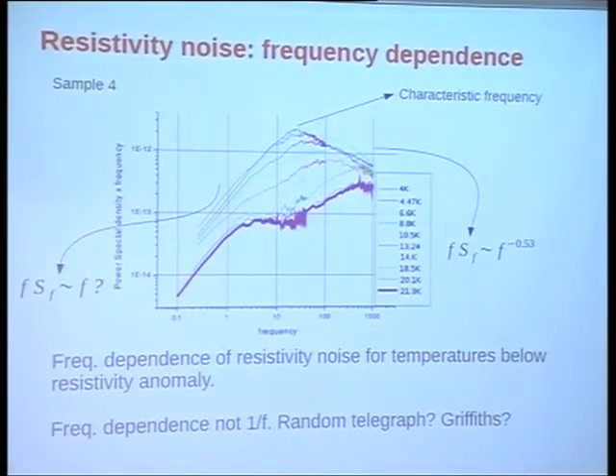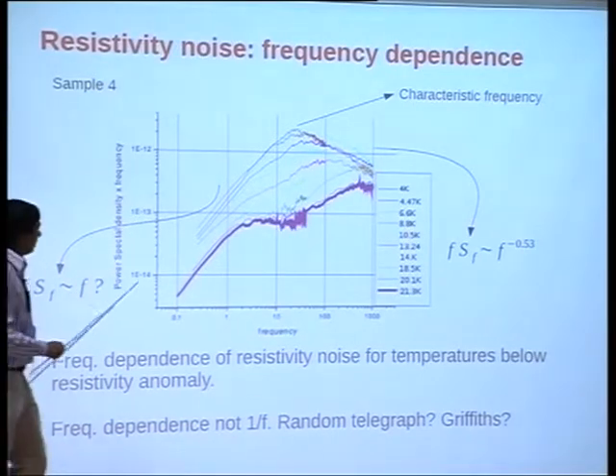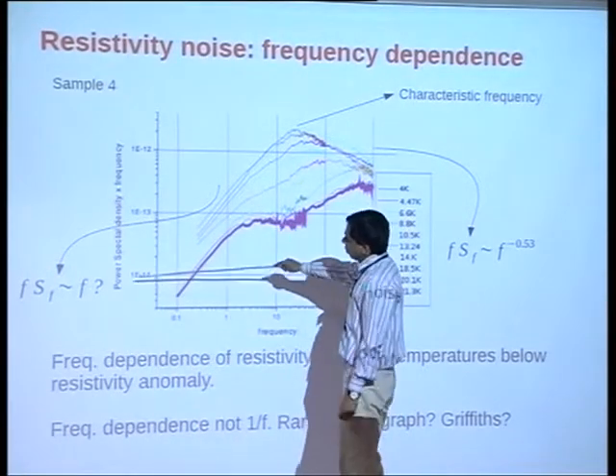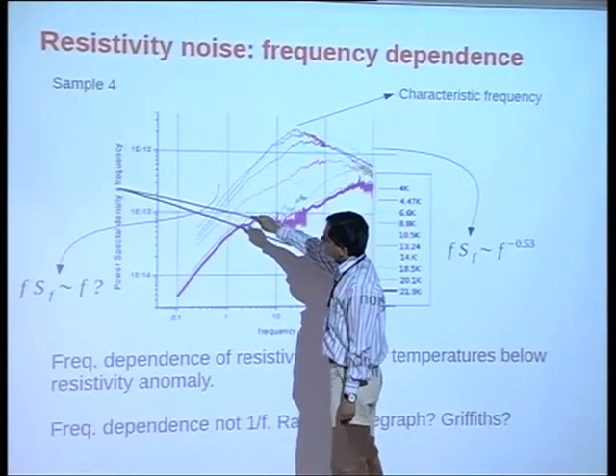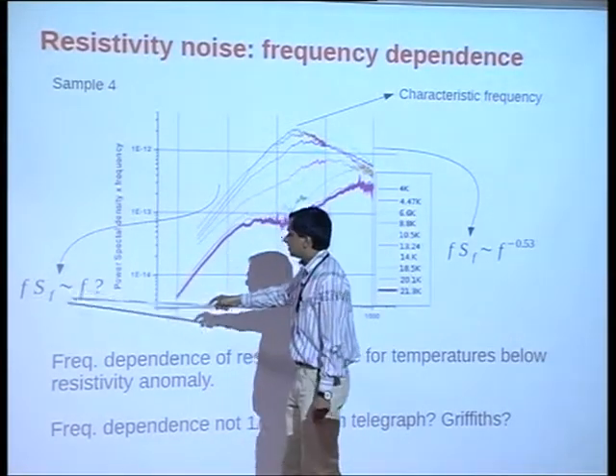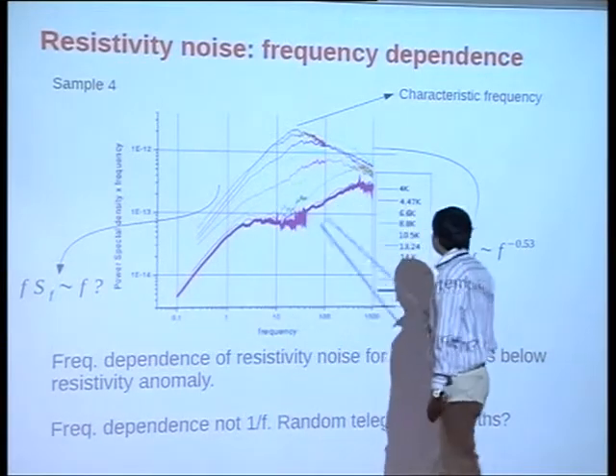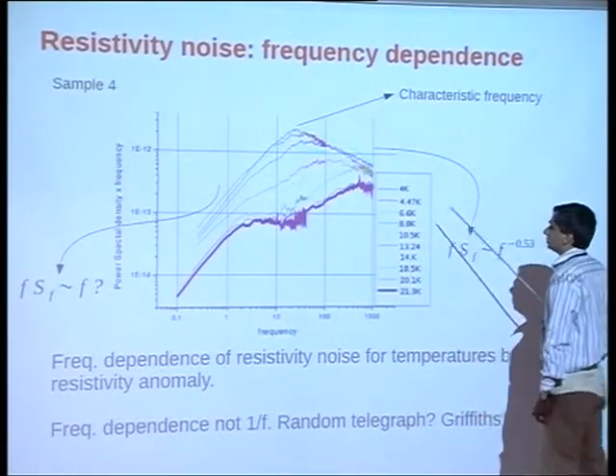Now let me show you some of the data on noise. This is sample 4, which is quite close to a metal insulator transition, and to us it looks more on the insulating side. If you remember, the resistivity curve was all along insulating for this one, although at a smaller value and a smaller rate of increase than the insulating sample 1. And here is a plot of the power spectral density times frequency, so it's F times S_F. S_F is the resistivity noise, and it shows a highly non-monotonous behavior.